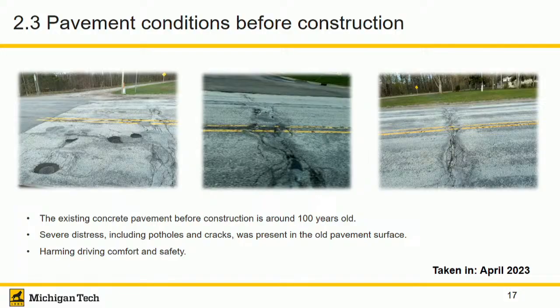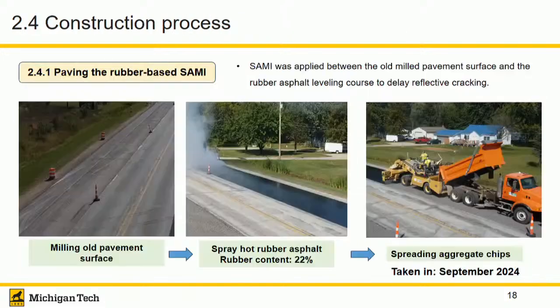So here is what we did. Okay, so first we need to mill a little bit off. Roughly, we milled 2 inches, so about 5 centimeters, of materials off. Right, so we mill it, and then we apply rubber asphalt materials on it. This is hot rubber asphalt, not emulsions. So then with that one, you apply chips.